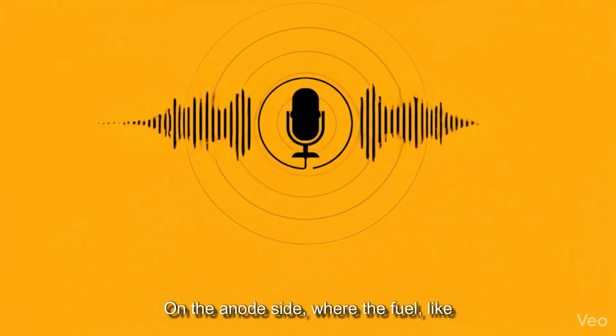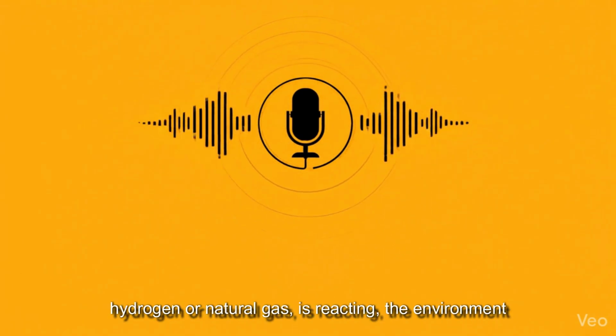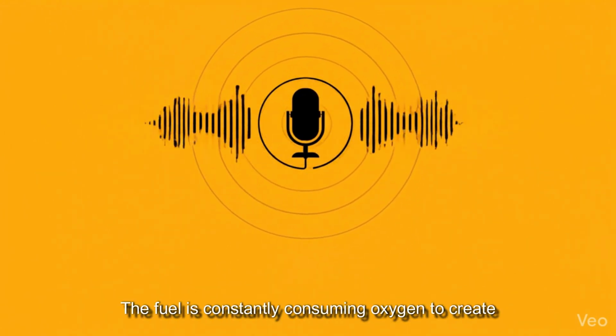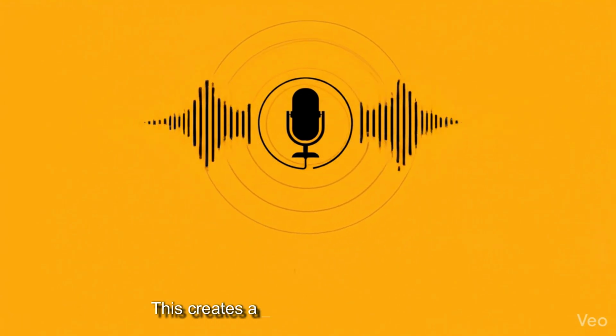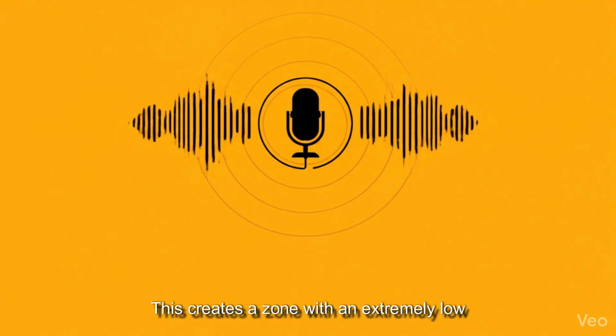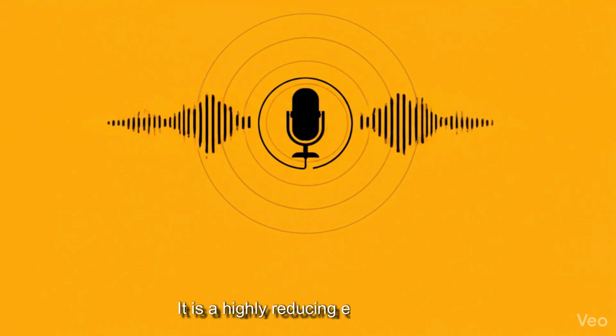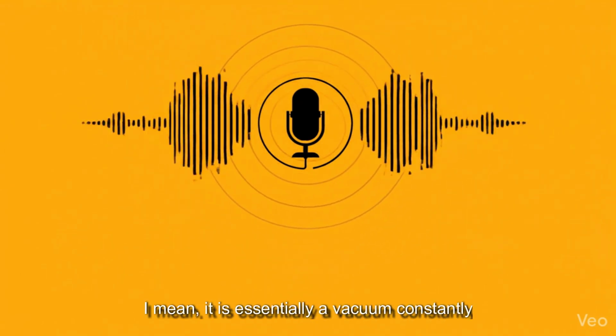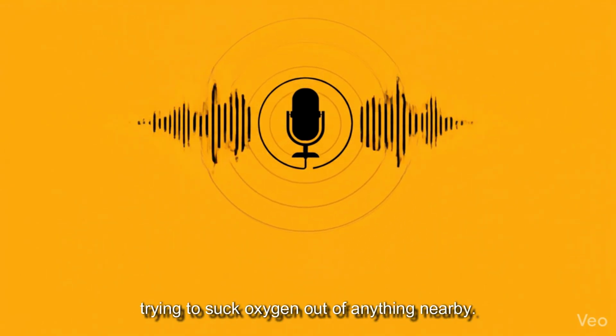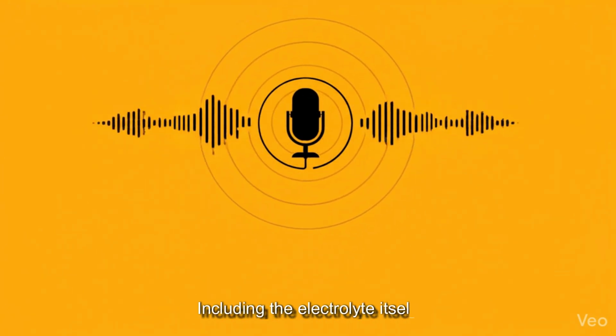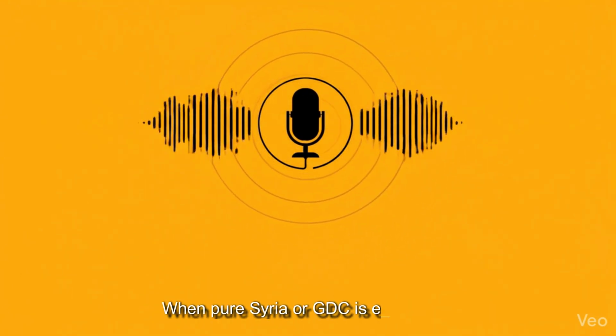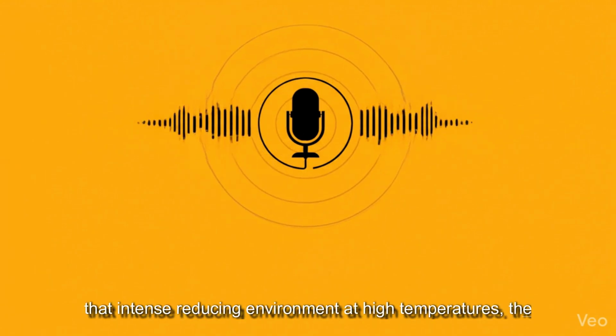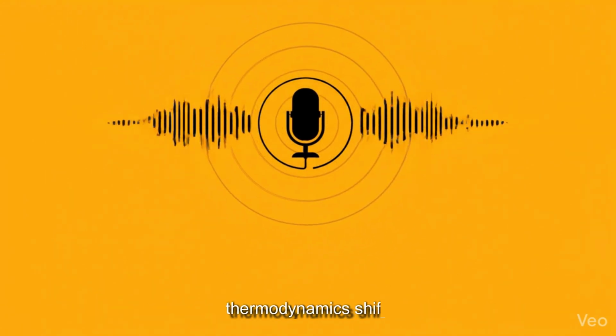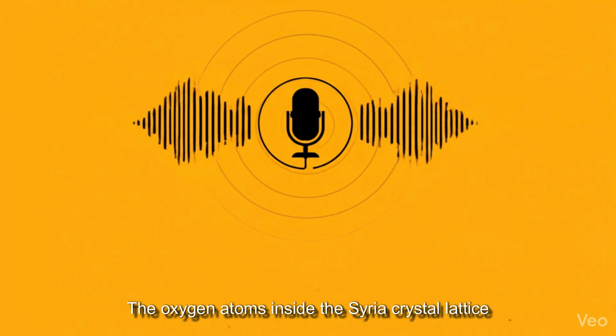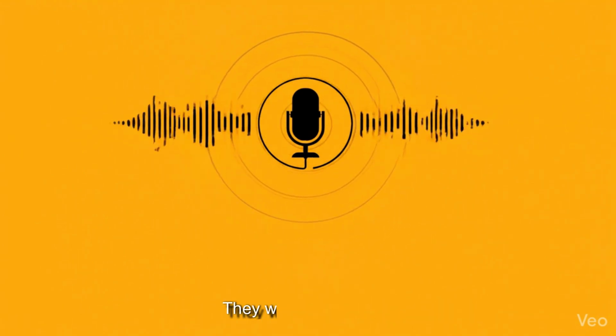On the anode side, where the fuel, like hydrogen or natural gas, is reacting, the environment is fiercely demanding. The fuel is constantly consuming oxygen to create water and electricity. Right. This creates a zone with an extremely low oxygen partial pressure. It is a highly reducing environment. I mean, it is essentially a vacuum constantly trying to suck oxygen out of anything nearby. Including the electrolyte itself. Oh, wow. Yeah. When pure ceria or GDC is exposed to that intense reducing environment at high temperatures, the thermodynamics shift. The oxygen atoms inside the ceria crystal lattice are tempted to leave. They want to jump out.